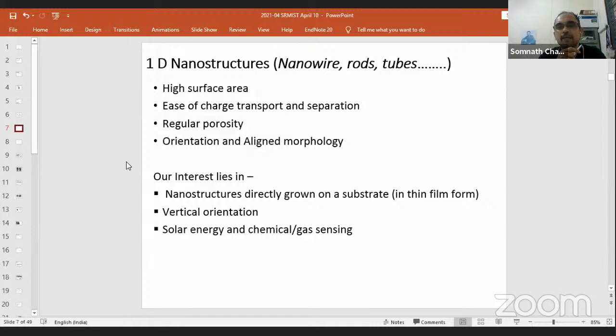And the other point is that we are interested in growing them from a substrate, as I said in the first slide. If you grow them vertically aligned, one after another like this, all aligned together, then it's much easier to control the morphology and predict the properties compared to a randomly oriented nanoparticle powder, or let's say some nanostructure randomly lying horizontally on the substrate. Those who work on carbon nanotubes may feel offended. Compared to that, if I have this aligned nanostructure like bamboo sticks all grown from the ground, it is a much easier morphology. That's why we said nanostructure directly grown on a substrate, vertical orientation.